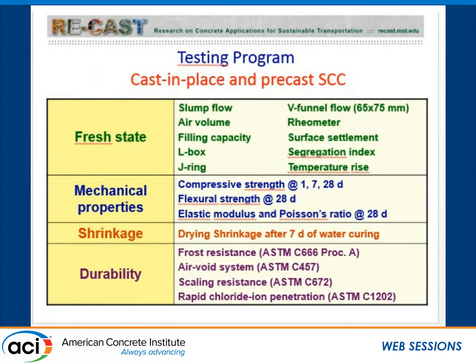And the concretes were extensively tested for fresh properties, all the workability characteristics for SCC, but also using rheometers for plastic viscosity, yield stress. We even looked at the thixotropy. Mechanical properties, we looked at compressive strengths, flexural strengths, elastic modulus, drying shrinkage. After 7 days of water curing, we did the drying shrinkage. And for durability, we looked at frost durability, air void system, deicing salt scaling, and the rapid chloride ion permeability test. And again, this was before the bulk resistivity and surface resistivity.